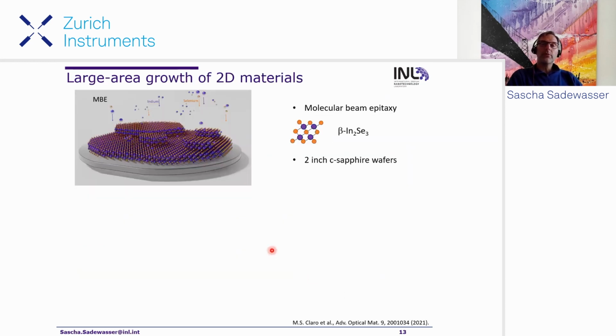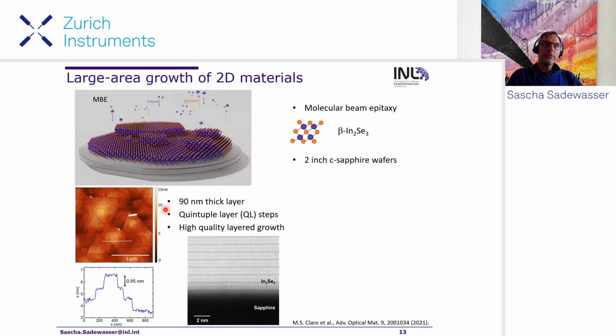So in view of this, we are working on molecular beam epitaxy, where we evaporate indium and selenium onto 2-inch sapphire wafers. And here's the structure. So the indium 2 selenium 3 beta phase is essentially 5 atomic sheets with the selenium, indium, selenium, indium, selenium. And when we do this, we get here an AFM image. So this is just a simple AFM, no KPFM in this one. We see these atomic scale terraces, each quintuple layer. So these are called quintuple layers, about 1 nanometer, and we get this atomic layer resolution here with the terraces.